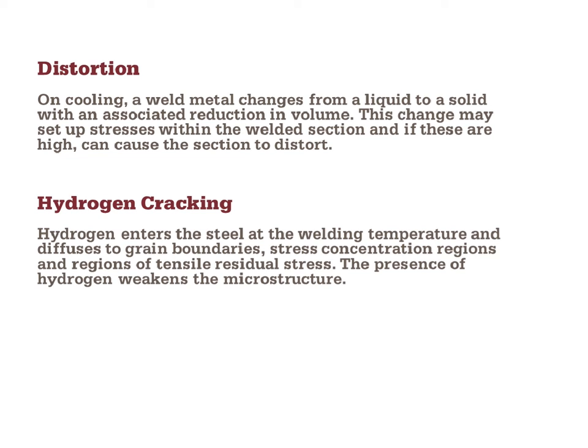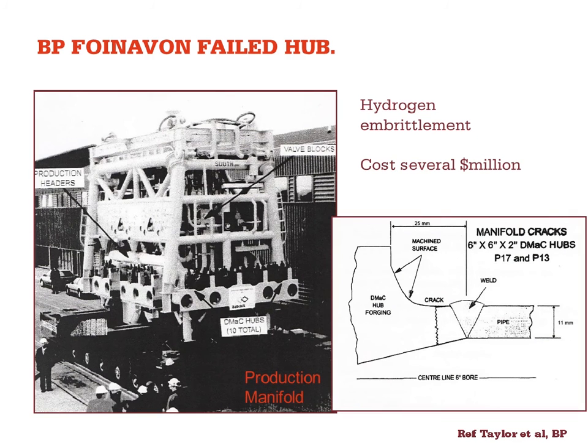When I talked about thermal contraction in casting, the same is true after welding, so we will have distortion to deal with. And also, very importantly in steels, we have to be very careful to keep any hydrogen away from the product. So in the manual metal arc process, where I mentioned that we have a flux coating, those welding rods have to be heated in an oven for about an hour at 200 degrees C to drive away any water, because any water or moisture will break down, form hydrogen, which then migrates into the weld pool and will very significantly weaken the structure.